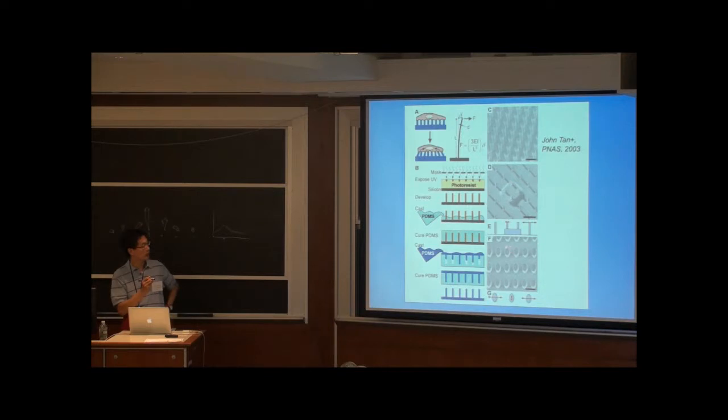You can make, for example, pillars that are not round. So you can imagine if a pillar is not round, then the forces to pull in one direction versus the other are not the same. It's anisotropic. And Benoit Ladoux has been using these kinds of substrates to look at what happens if the stiffness of the surface is not isotropic.